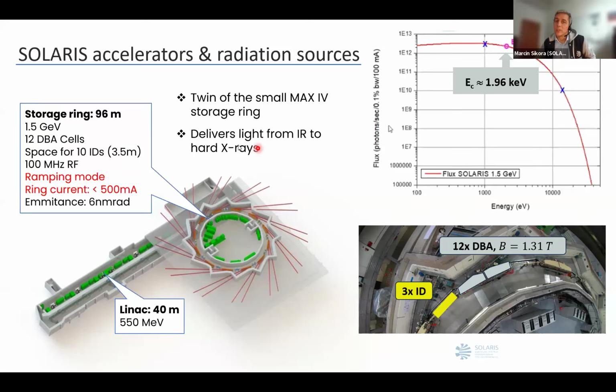We deliver light from infrared up to hard X-rays. When you look at the spectrum from the bending magnet at Solaris, the critical energy of photons is about 2 kilo electron volts. As you see, the intensity is pretty good, especially in the soft and tender energy range. For hard X-rays it's a little bit lower, but fortunately, thanks to undulators like the one from PSI, we can increase our flux a lot.